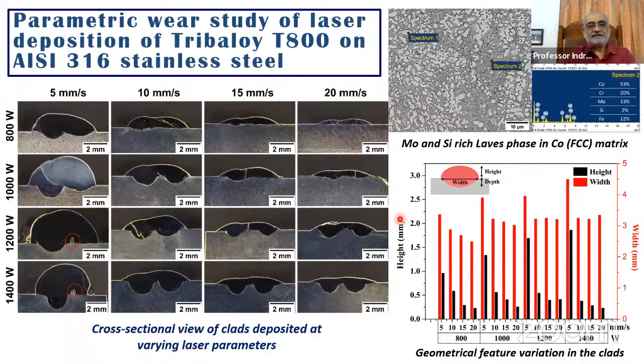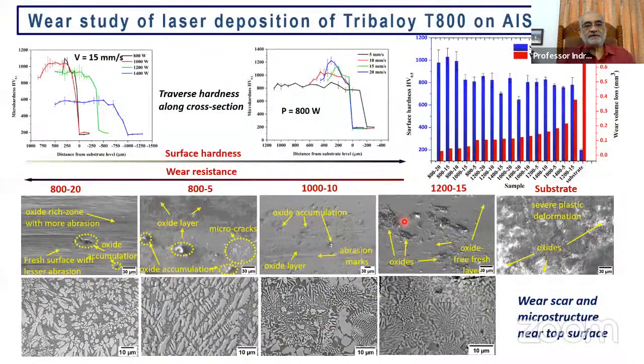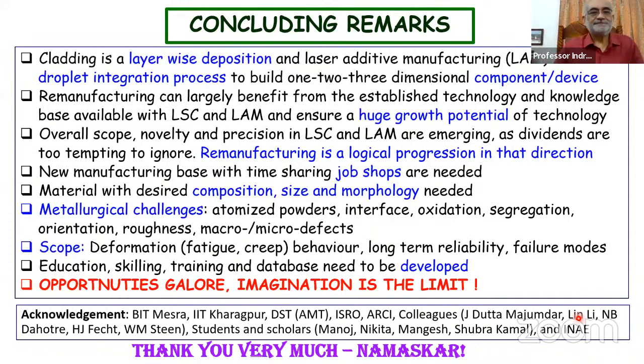So I'll skip this part. This is the wear, volume, and tribological aspects of this entire cladding process. This is also very interesting because, as you can see here, the red bars refer to the wear, and the blue bar refers to the hardness. So it's not always true that high hardness means higher wear resistance, but here we see a nice correlation that with stainless steel substrate, we have the highest wear volume because we have the poorest hardness. On the other hand, when I have pure T800, then I have nearly the highest hardness and the least wear volume. So we have to play with it, and this is what you're seeing as a function of various laser parameters. So with this, I'll try and wind up now.